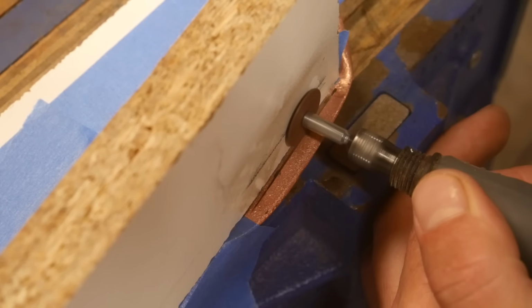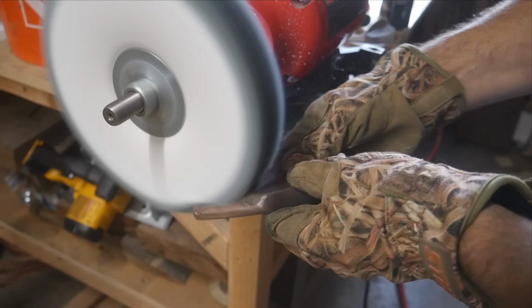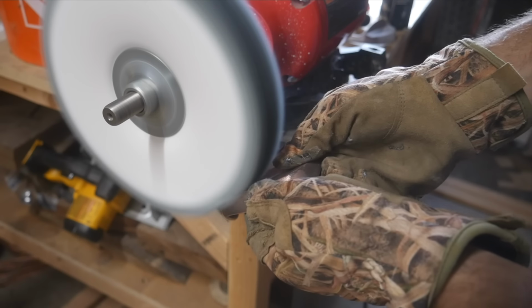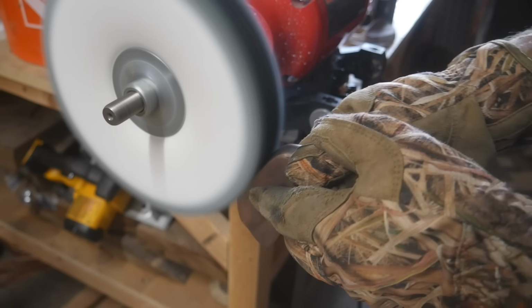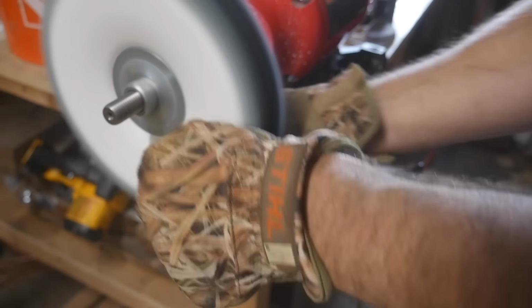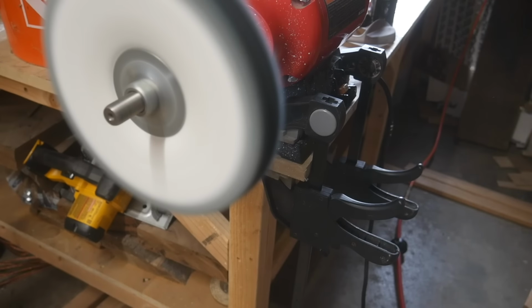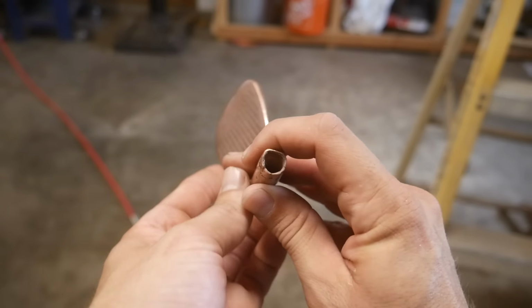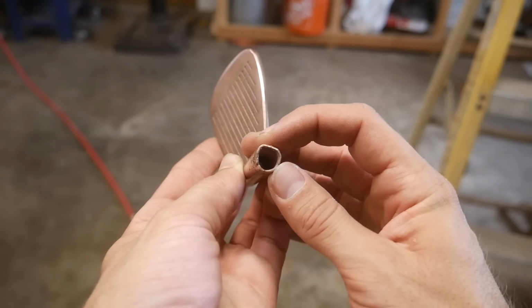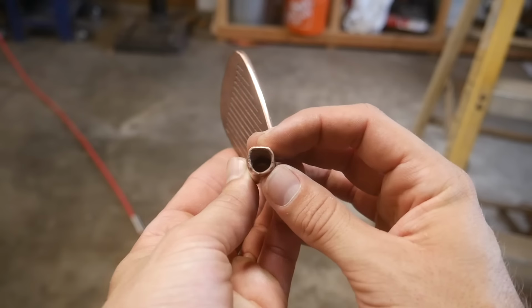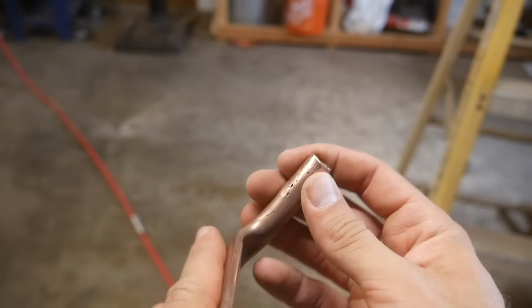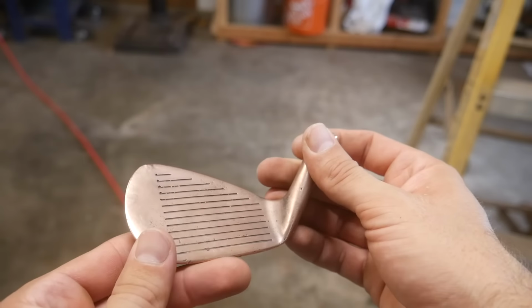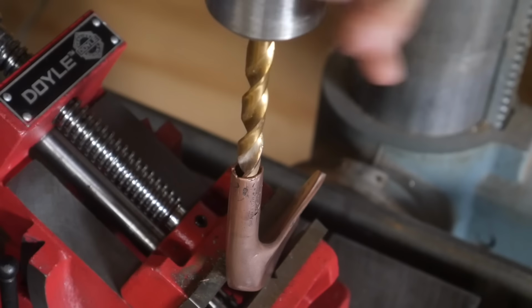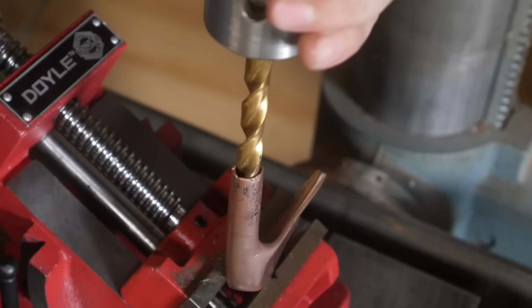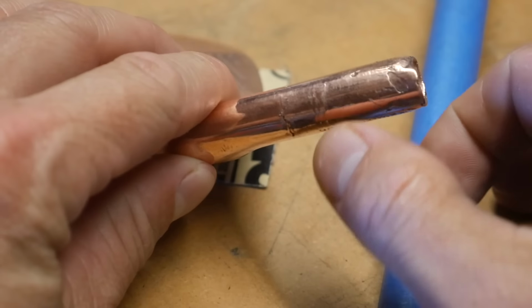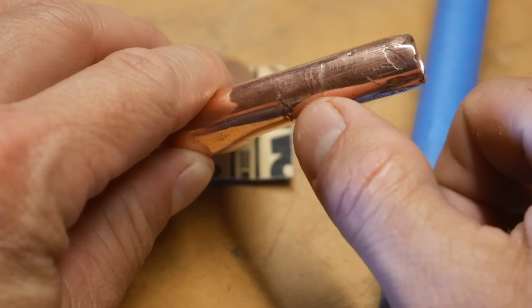After that, we polished it up on the buffing wheel, which is a bit challenging to do if you've never tried buffing an iron head on a wheel. Packard's first try polishing an iron on the wheel and got caught by an edge. Bent the hosel a bit, but really just mostly concerned with the overall strength of this thing as an actual golf club. We were able to straighten out the hosel on the drill press, but after doing so, we noticed a crack in the hosel, which was not going to fly.